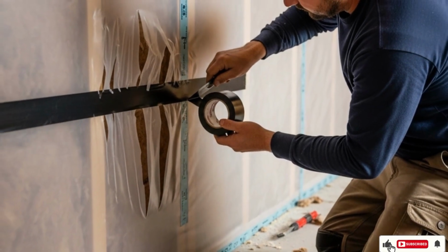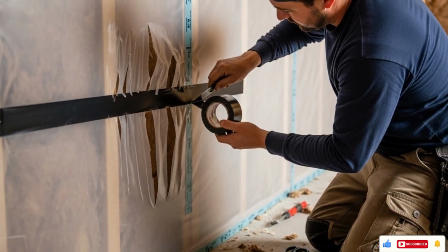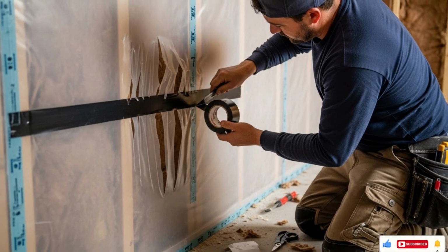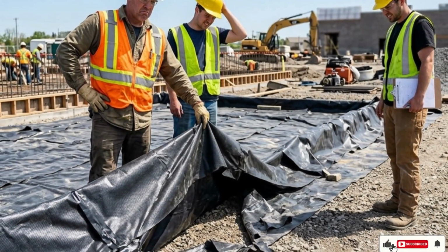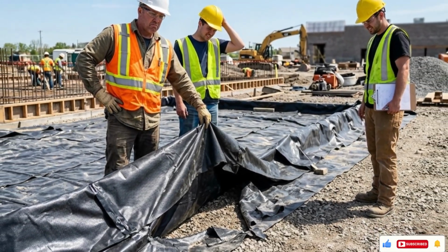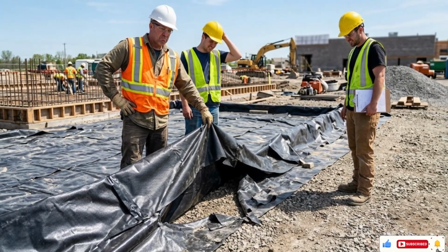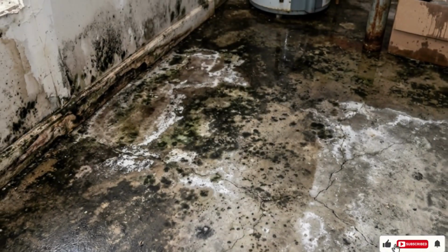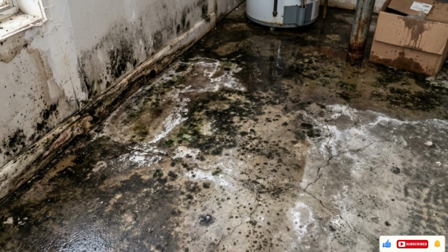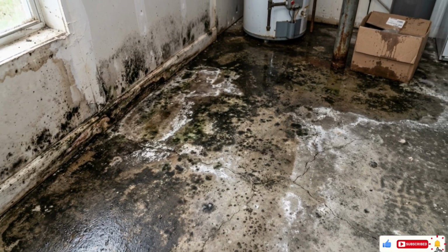This membrane is the last line of defense against moisture entering the slab from below, and the consequences of a poorly installed vapor barrier, damp concrete, flooring adhesive failures, mold under vinyl and carpet, efflorescence on the slab surface, appear months and years after construction, often after the builder has long since left the site.